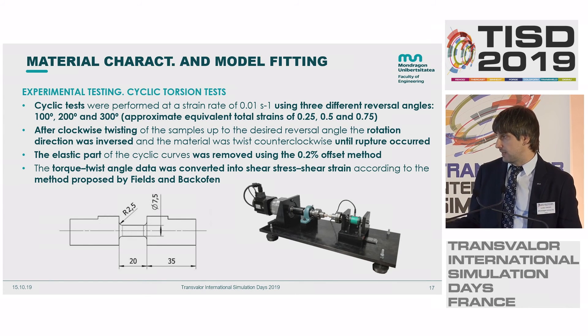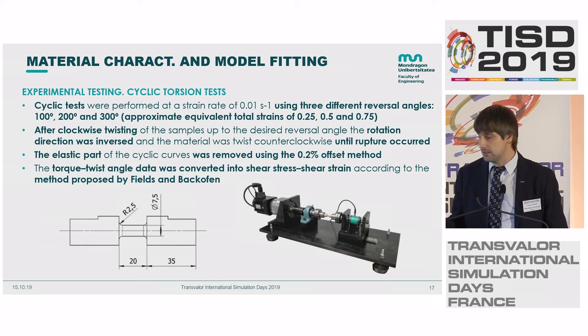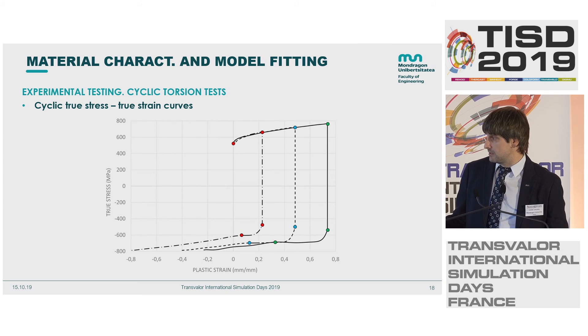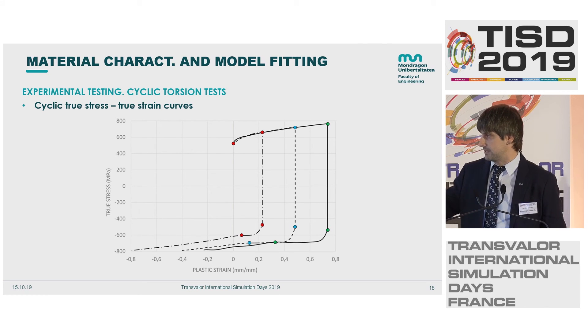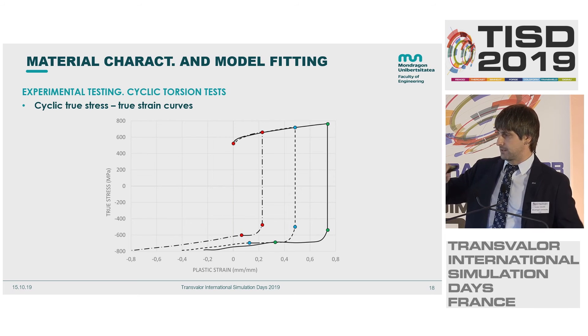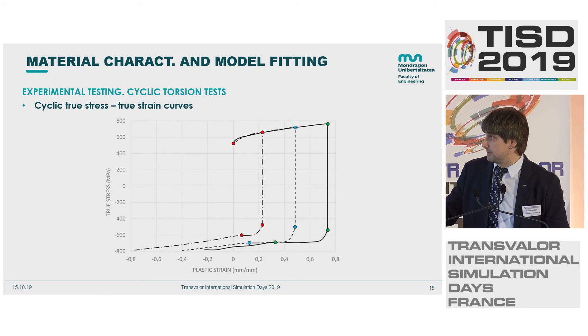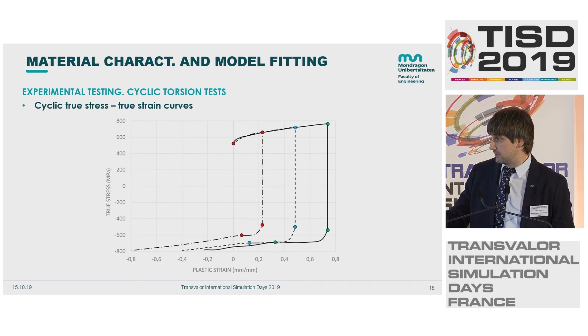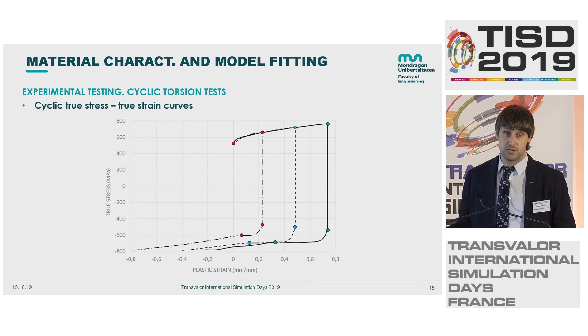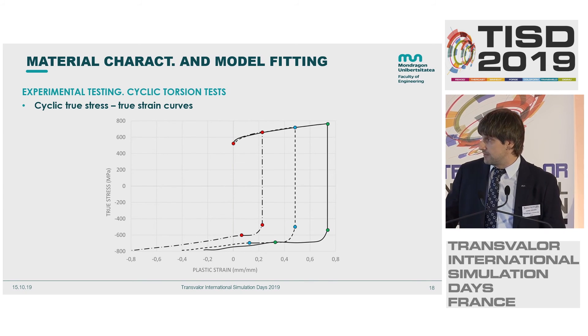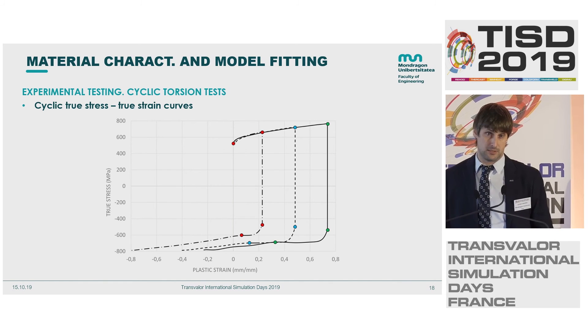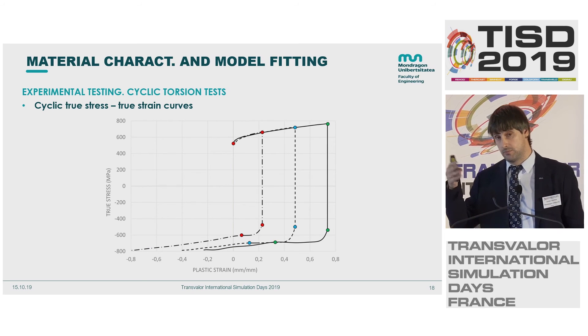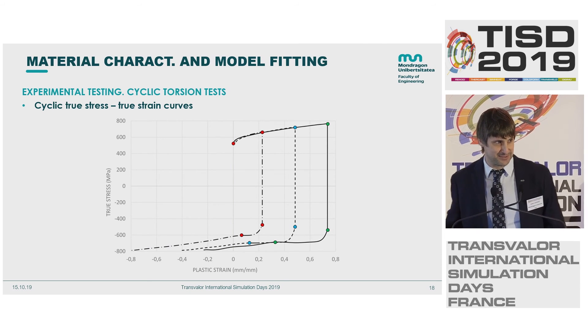We used classical formulas to obtain uniaxial stress-strain curves. From first pre-strain and re-twisting in both directions, you can see that re-yielding occurs earlier than in the first loading — the Bauschinger effect. With larger pre-strain, there is a larger plateau afterward, which is consistent with the state of the art.